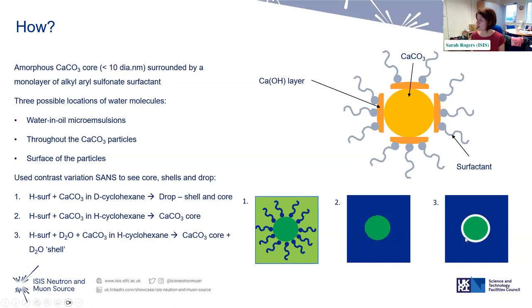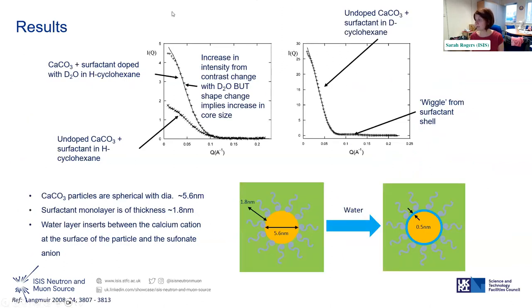And if the water was to go on the outside, that's what it would look like. So then when we actually did the measurements, the water does go on the outside of the particle. So these are the SANS measurements. We did lots of different contrasts, lots of different analysis. And basically we found out that the CaCO3 particles were actually smaller than they thought. They're only about 6 nanometers, but there is this sort of surfactant stabilizing shell around the outside.